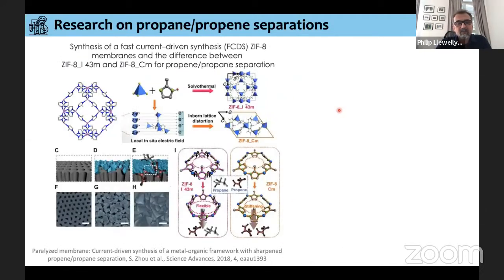The same type of idea is shown here. This is work which Jürgen Caro worked on, taking this material known as ZIF-8. As I alluded to right at the very start, some materials are quite flexible, and in this material we can see the linker can spin around on itself. What these people have done is make a membrane, using an in-situ electric field to make it. They say the membrane is fixed in a smaller pore system. So instead of having a system able to flex, they've tried to distort the lattice to make it a little bit smaller.